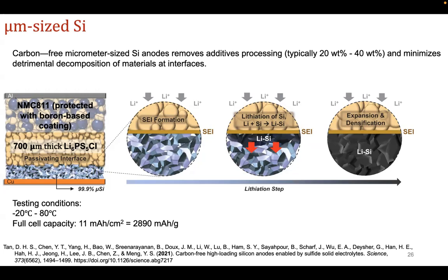And one of the reasons why we can come back to micron-sized silicon anodes is that instead of liquid electrolyte, so before, all the systems that I was talking about for the micron-sized powder of silicon interacted with liquid electrolyte. And during the pulverization step, what happens is the cracks form, and then you have now new surfaces where the solid electrolyte interfaces can form. Now, these SEI are not always advantageous for the cracked material. And on top of that, if you have a lot of cracking and pulverization, you're having more delamination, physical changes in your electrode material.